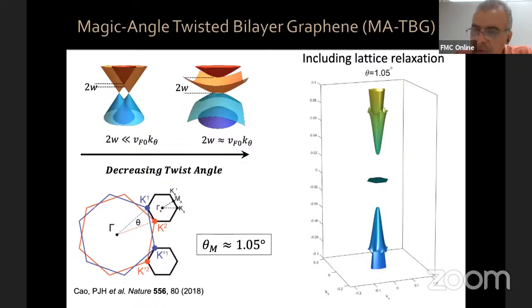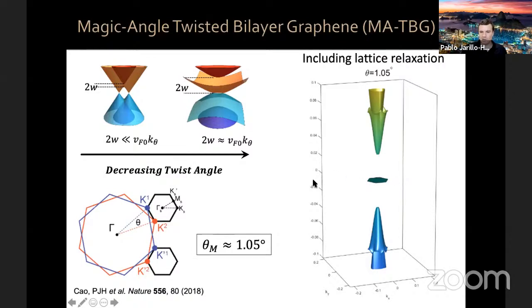Are there some favorable features of the single layer materials for showing exotic physics in the twisted configuration? So in the case of graphene, it is important that you can get these flat bands, okay? Graphene itself, just one layer of graphene, is not a strongly correlated material. In fact, in that Dirac cone, the kinetic energy of the electrons is very high, okay? So graphene by itself does not exhibit very pronounced correlated phenomena. When we put these two graphene sheets on top of each other at that angle, because of the quenching of the kinetic energy, you get this correlated exotic physics.